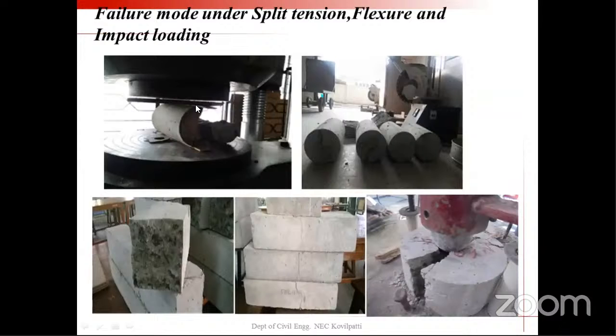And we can stand very boldly near the equipment and do the testing when we are doing the FRC. Whereas while testing the control concrete, we used to be scared about when the specimen will fail, because it's a sudden explosion. Already it is M45 grade concrete, so the ultimate strength will be 65 MPa, 70 MPa. So when you're doing the testing in FRC, no need to worry, because the failure is very gradual and only ductile, and no need to worry about the testing methodology. We can do the test in a very safe manner.